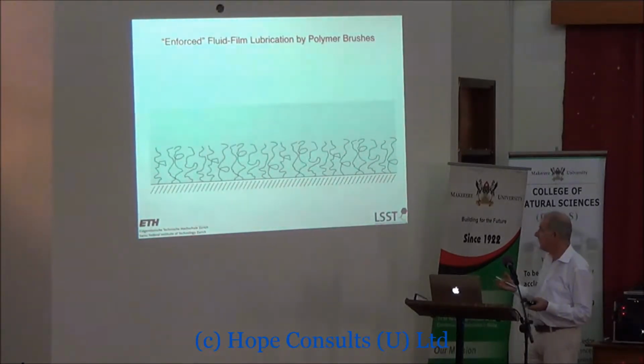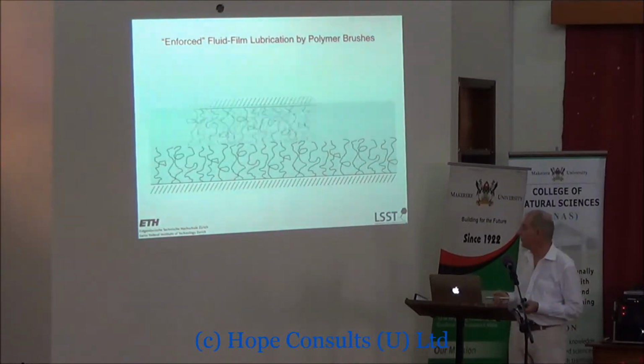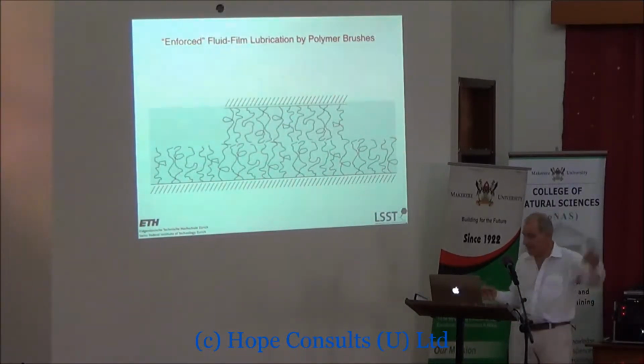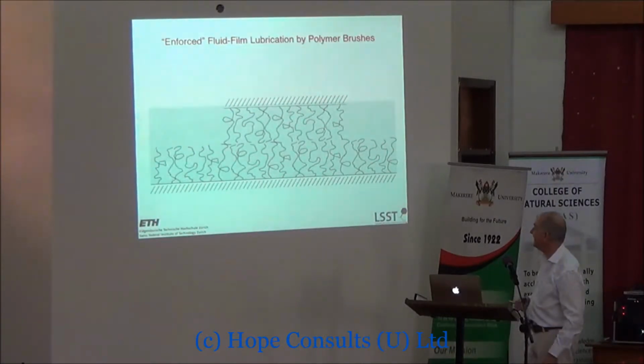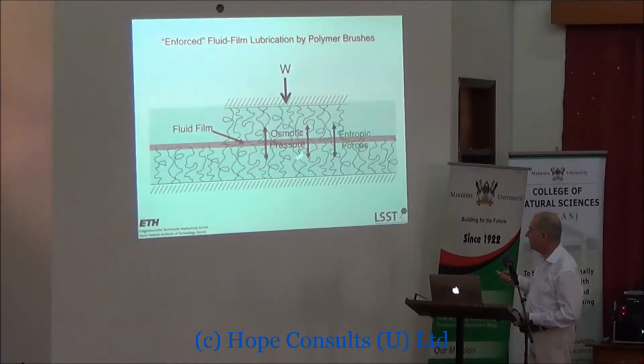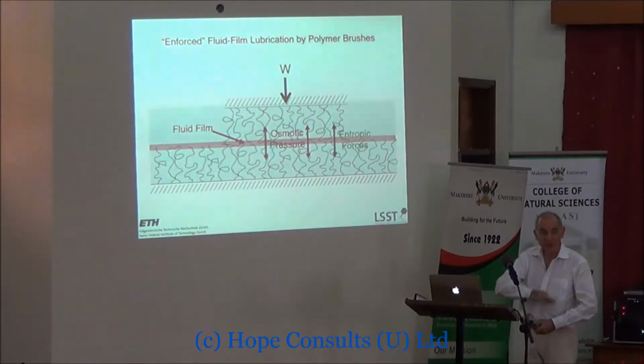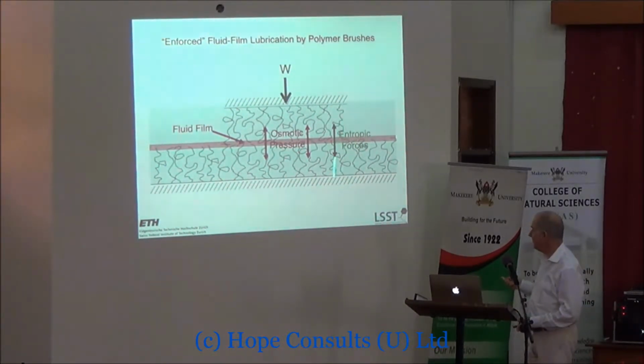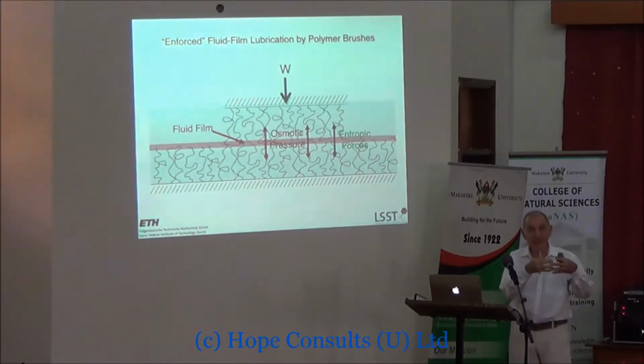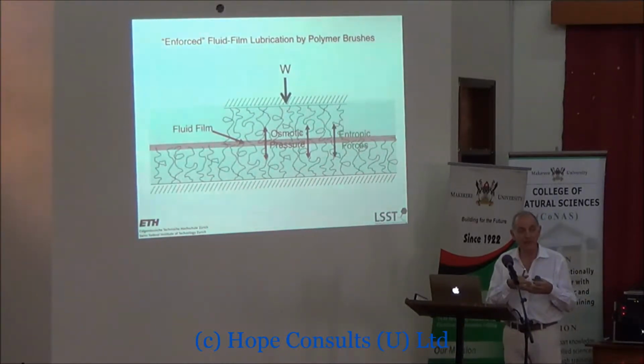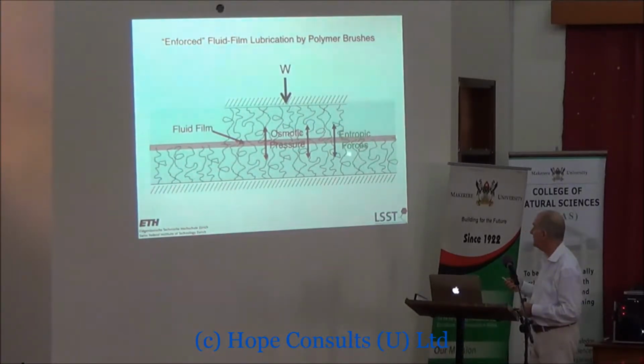Now what's happening when we slide one polymer brush layer over another polymer brush layer? This came from Jacob Klein, the guy who was doing this in the picture I showed you earlier. We have several forces at work. We have osmotic pressure, which will inhibit the compression of these polymer brushes. And then we have more entropic forces that prevent the interdigitation of these chains. Because if they interdigitate, then you restrict the configurational entropy of these polymer chains. And so there's a free energy term that stops that happening. And so there are really two springs, if you like, that stop these two hard surfaces coming together, and they're prevented by these soft surfaces, the polymer brushes.